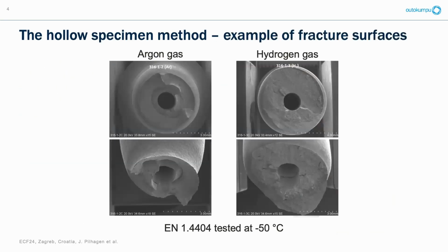And here's an example of the fracture surfaces. This is 316L, 1.4404, tested at -50. You have the argon gas on the left and the hydrogen gas on the right here. And we can clearly see this kind of embrittlement in the hydrogen gas environment.